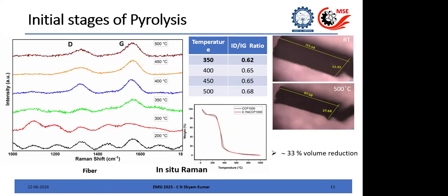At what temperature the biomass is converting into carbon, where the mixture of sp3 and sp2 carbon is forming. We can understand this with the Raman, and from this we can say that it is somewhere around 350 degrees Celsius. And from the TGA, we can see that the maximum weight loss is happening between 300 and 400 degrees Celsius. So it is when the volatiles are removed and it is becoming carbon. This is with coconut coir, and similar things can be expected, because the graphitization trajectory will be similar. There might be some shift in the temperature, but you can expect a similar trend on the other